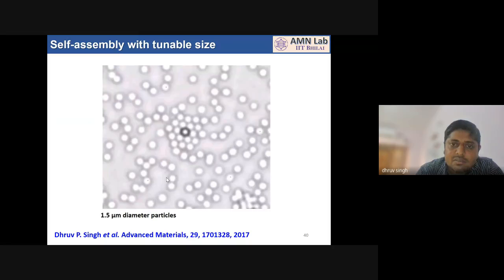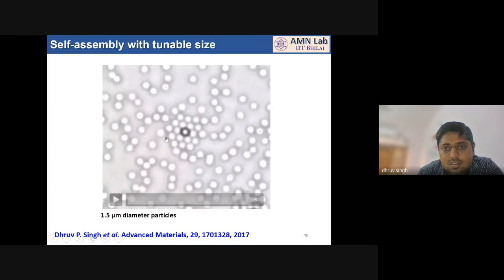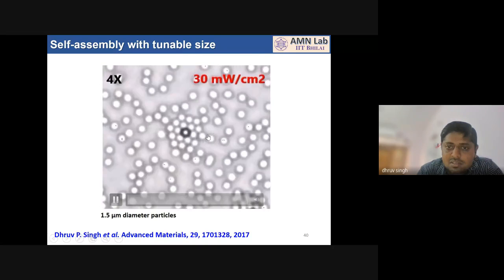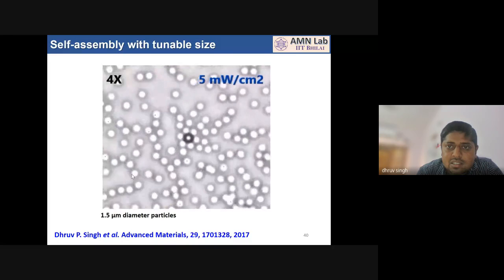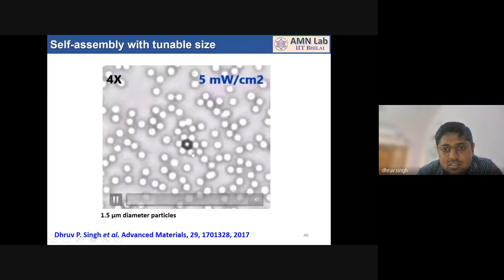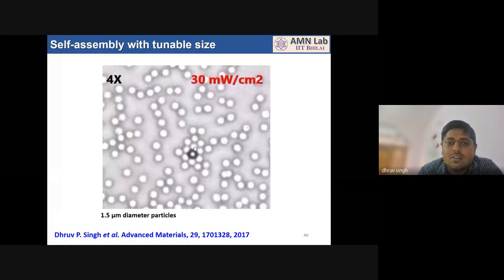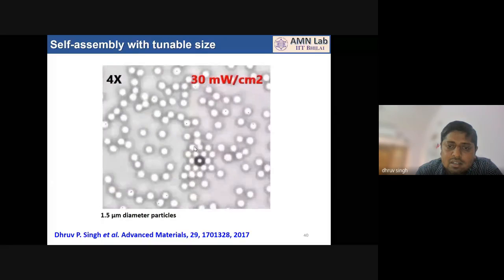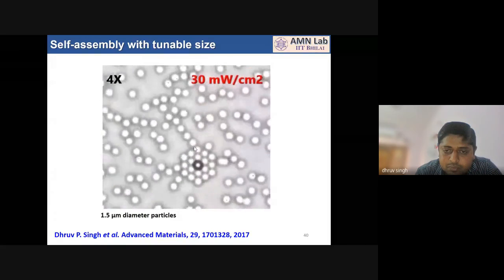Like here you see, we have a big hexagonal structure formed around a single nanomotor, this one in the center. Right now it's formed at the higher light intensity, so interaction strength is high. A single nanomotor can collect the particles up to this distance, or 2 layers of the passive particles. But if you decrease the intensity of light, interaction strength is reduced. So if we chop off the second layer, only the first layer is left, and the size of the structure is reduced. If I increase the light intensity again, then I get the second layer back. So I got the bigger size again.